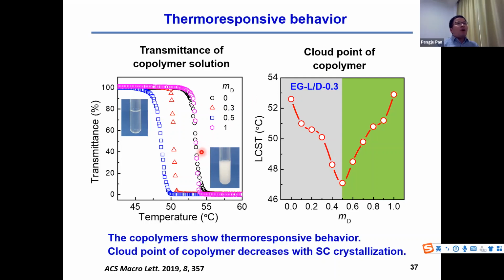The cloud point of the copolymer solution can be controlled by stereocomplex crystallization through changing the mixing ratio of L copolymer and D copolymer. The homocrystalline copolymer shows a high cloud point, but the stereocomplex copolymer has a low cloud point, even though they have the same concentration and the same copolymer composition. So we can control the cloud point in a wide range by changing the mixing ratio of L copolymer and D copolymer.